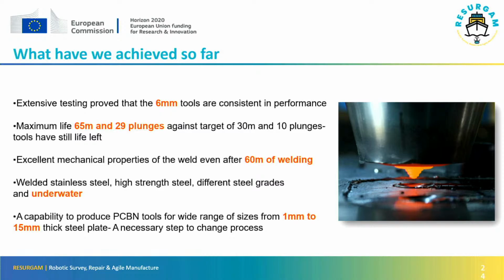So at the moment, we've found that their tools designed for welding 6mm thick steel will last for at least 65 meters of welding, and they will go through 29 plunge cycles. So that's where you drive the cold tool into cold steel, where you've got incredibly high forces and abrasion. The target was 30 meters of weld and 10 plunge cycles. So they've exceeded the targets quite easily. The quality of the welds was still good even after 60 meters of welding.